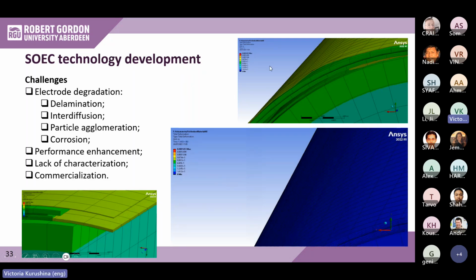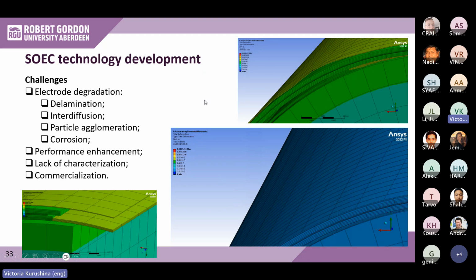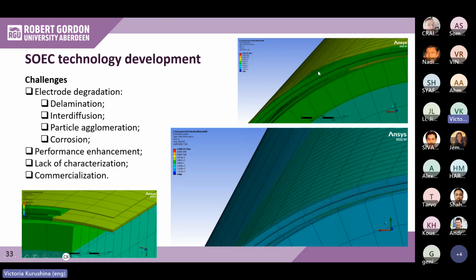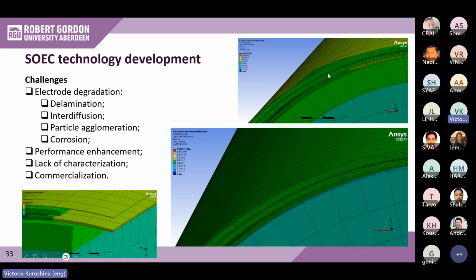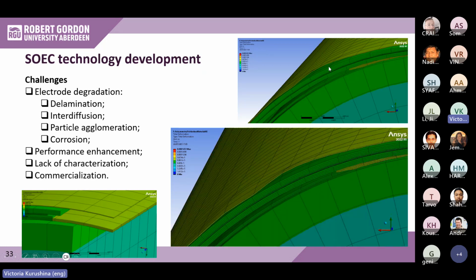Related to this, if you take a cross section and try to visualize how these layers grow, you can already see the potential for delamination when the layers become separated at some distance from each other at the microscale. So it lays the foundation for the development of many degradation effects, delamination, or some lack of performance, because what happens at this microscale significantly affects how the cell is going to perform overall.